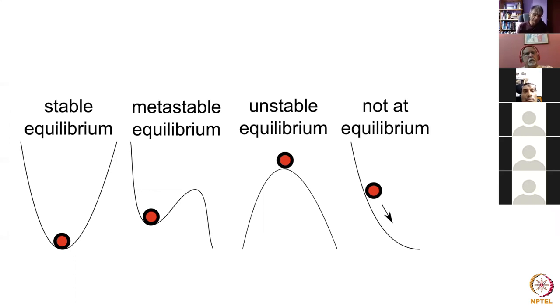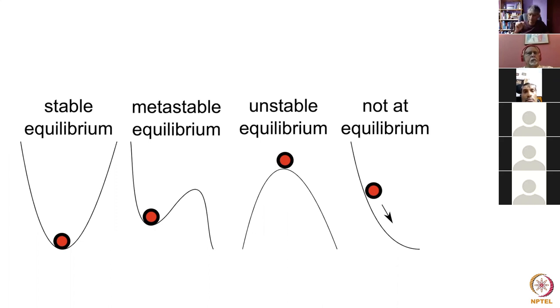There may be other minima in the system, so this here is known as metastable equilibrium, but from the point of view of thermodynamics we don't differentiate between the two, because if I give an infinitesimal perturbation to this ball it will return to its original position and we never know what the lowest minimum is. There's no difference from our point of view between metastable and stable equilibrium — we cannot actually say something is at stable equilibrium because you might find a lower minimum somewhere.